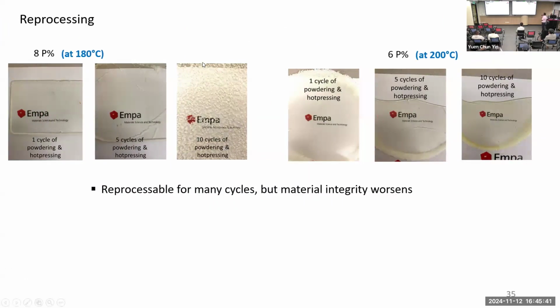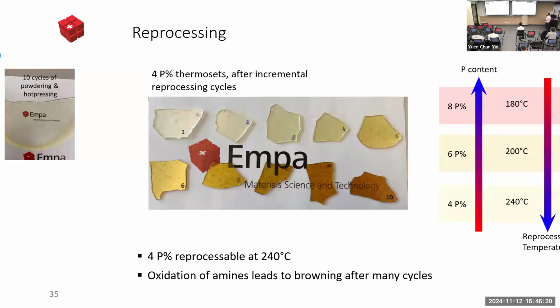Here you can see we do have challenges as well. When you have higher phosphorus content, it's easy to recycle them, but then after 10 recycling cycles, you see this blooming effect, which is something we need to consider. Whereas for 6% phosphorus, 10 times recycling is possible, but we also see side effects: the material integrity goes down. So this is something we are trying to understand, why this is happening. Obviously, you can recycle them, but we want to have a recycled product with similar material integrity. So we are still understanding what's going on there.